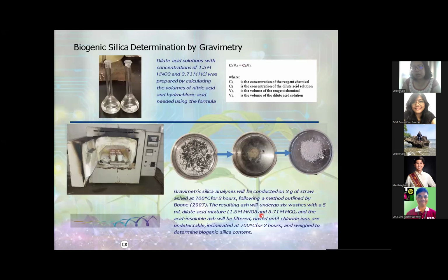Actually, this is what was supposed to be pasted. But I only did one wash, and it wasn't a controlled manner; I just estimated 5 ml, though I did it slowly. And then the acid ash is filtered until the chloride ions, detected as precipitate of AgCl, are undetectable. It is incinerated again at 700 degrees Celsius for 2 hours and then weighed to determine biogenic silica content.